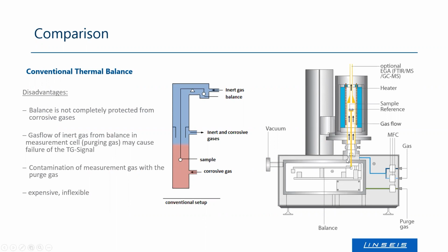I will shortly explain that. So usually you have the housing. This is the unit down here. In there, you have a vacuum-tight balance block containing your microbalance. This microbalance is holding this yellow sample rod that goes directly into the furnace. So on top of the yellow rod, you measure your sample. Maybe even you have a DSC rod, and you can also measure, of course, TG-DSC here. Sample is heated. The sample sees gas from these gas inlets. Usually it's mass flow controlled. So you see a gas inlet, you see a gas path, you see a gas flow passing the sample. And usually you have a purge gas purging your balance chamber down here. The purge gas rises up here, goes out at the flange. The sample gas goes into the tube, is released at the top. And therefore you have almost no intermixing, but there is a risk of mixing the gases directly at the flange where the one chamber is connected with the other chamber. And there is a physical connection needed because this rod has to physically be attached to the balance unit.